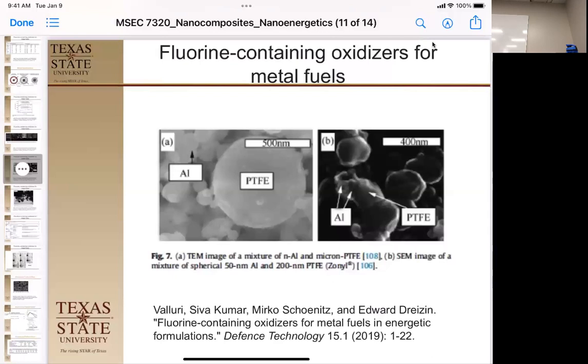And what they were able to do is get a much more dispersed, intermixed oxidizer and fuel. Here, these have the big pellets and the little teeny aluminum, but huge chunks of PTFE. So you have a much better oxidizer fuel mixture here. So therefore, it should have a faster combustion rate.